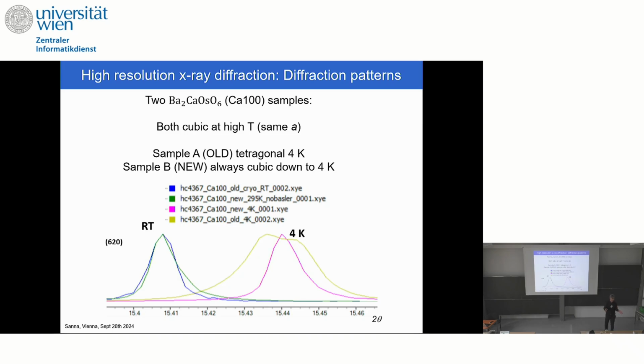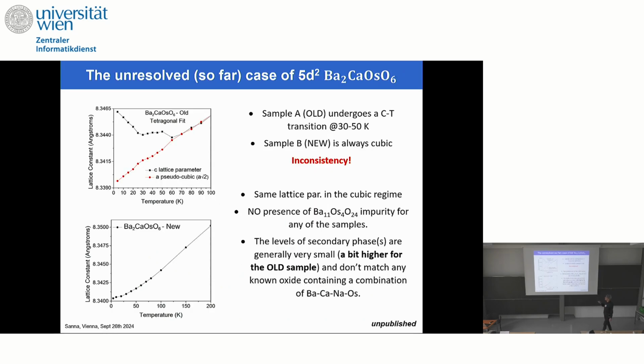But when we cool down these two samples, let's call A old because it became first, B new because it became later. This is at room temperature. When we cool down, the B sample has a single peak, which is simply shifted because of the shrinking of the lattice parameters with temperature. But the A sample at 4 Kelvin displays a very nice splitting. Not very well resolved, but it is a splitting. So it means that it is in a tetragonal structure. And so we can detect that this cubic to tetragonal transition does occur around 50 Kelvin, close to the magnetic transition for this sample.